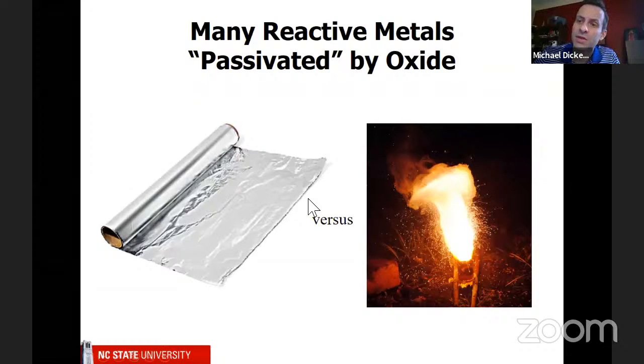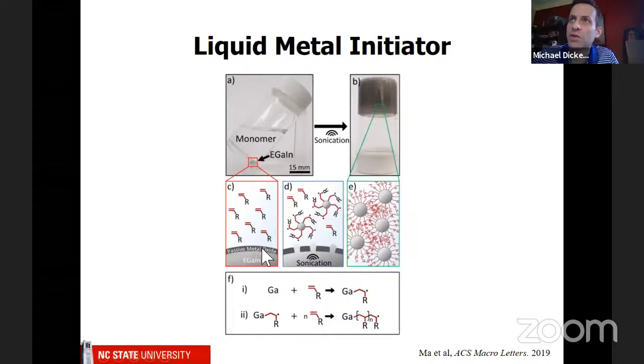So the idea here is that certain metals, which are very reactive, actually don't react because of the oxide. In our case, if you focus right here, this is again the oxide layer with the liquid metal, and these red things are the monomers, the molecules. And what we think is that when we sonicate it, we break the oxide and we expose this very reactive metal to these monomers, and we start to form polymer, which again are these long chains. To be honest, we don't completely understand this mechanism, and it's something we're still trying to figure out, but I'll give you some of the things that we do know.